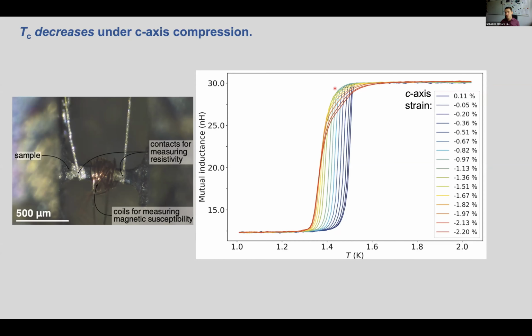This feature here, this tail here, does not reproduce in a second sample, but this decrease does. So I think that's the intrinsic response to c-axis strain. This is an artifact of some in-plane strain due to the sample bending or due to imperfections in the sample. We don't know exactly, but it's an artifact.